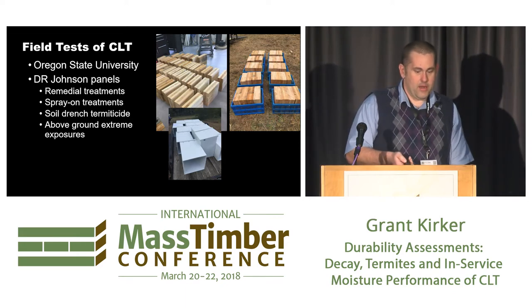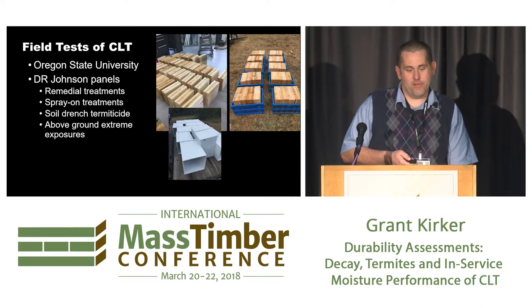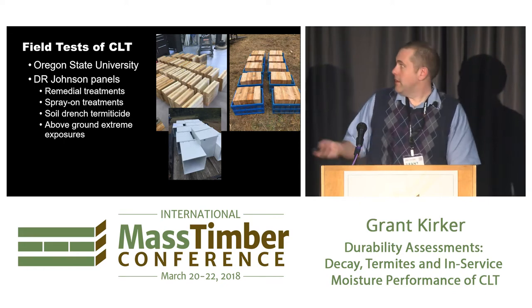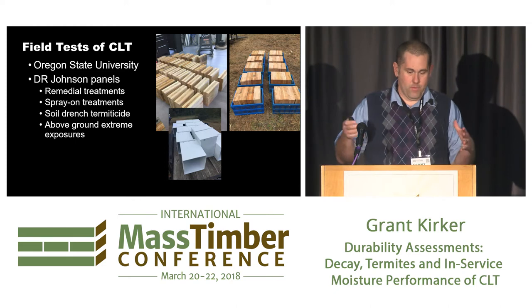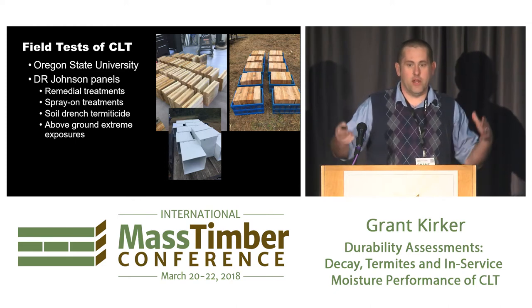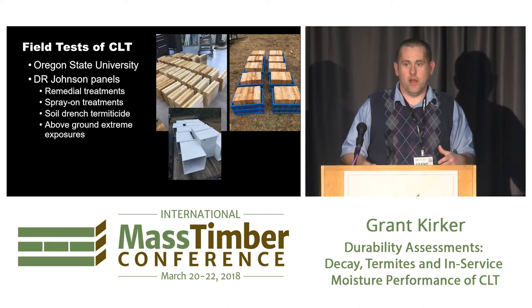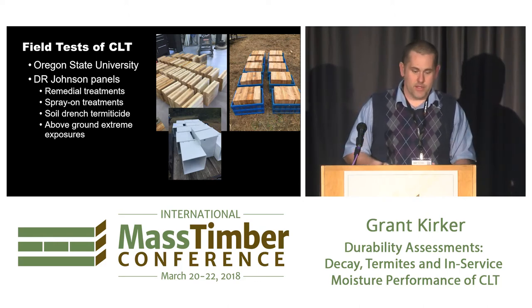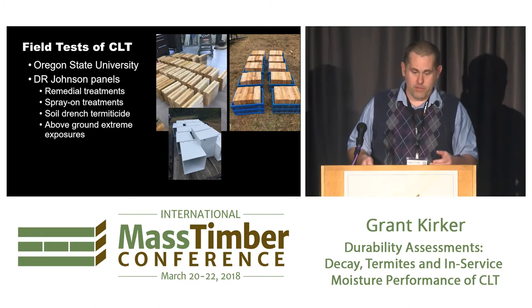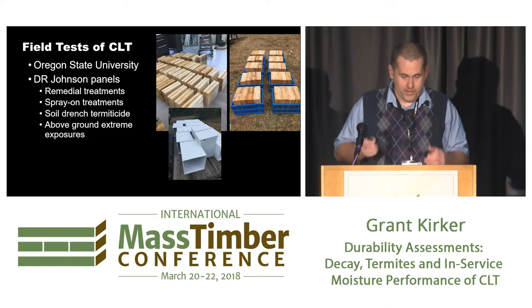And then we've also kind of modified the AWPA E21 test to simulate some severe above ground exposure. And that's what these are. It's basically a white box that's painted, so you get no airflow in it, and you just put that over the CLT, and so it just bakes in there. It's really high humidity, high heat, and it's a very severe test. You get tons of mold, and hopefully we're going to get some decay in there too, so they should be really awful when we pull them off, but we're not touching those for a year.